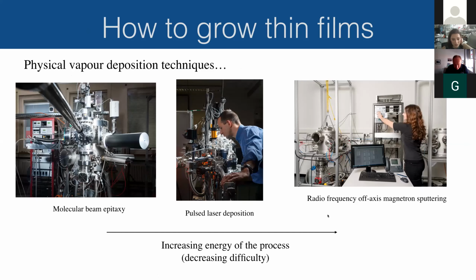So how do you grow these things? I will not go into too much detail on this, but there are very many methods for growing. In our lab, we are using a range of physical vapor deposition techniques, which means that the ionic species, which are eventually going to become the film, are transferred to the substrate through some process, and the process depends upon the way in which you are growing. For example, there's molecular beam epitaxy, where you often have the individual elements, and you heat them up until they reach their evaporation temperature, and then they just go out into the chamber. This is an ultra high vacuum chamber, until they find the substrate, which is nearby.